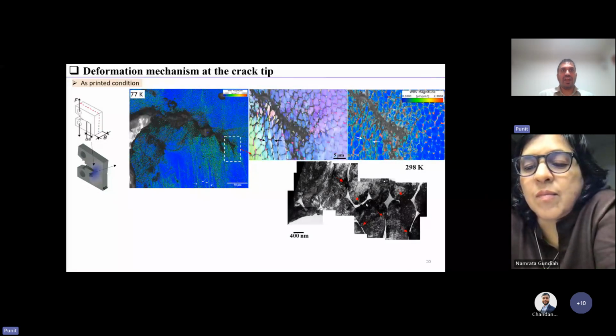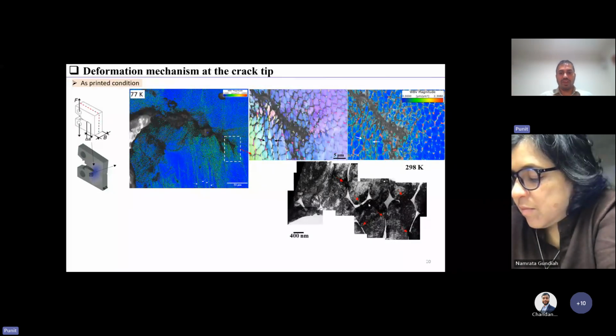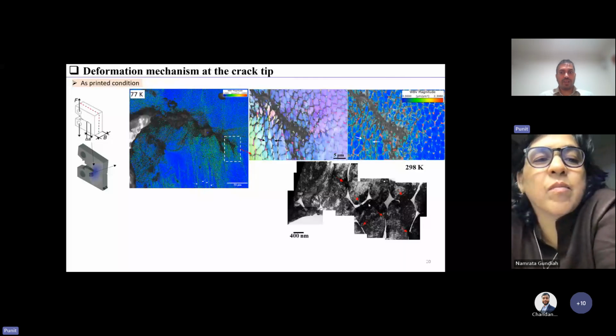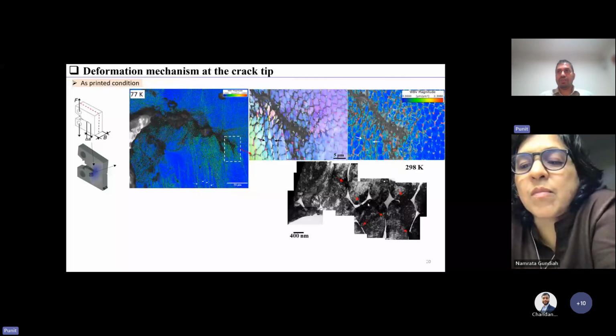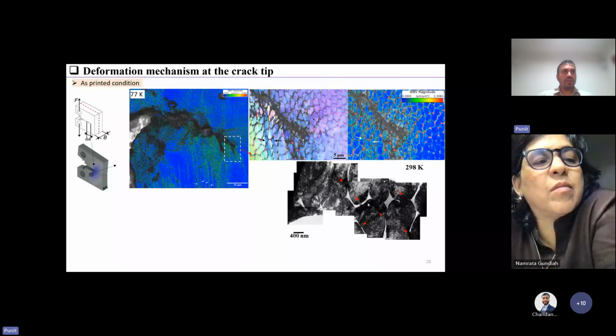Essentially, in the end, that's how the material will fracture, after a lot of deformation that the material undergoes before the crack nucleates on the B2 phase boundary. And I think the second part of your question is how do we achieve this microstructure during the heat treatment.